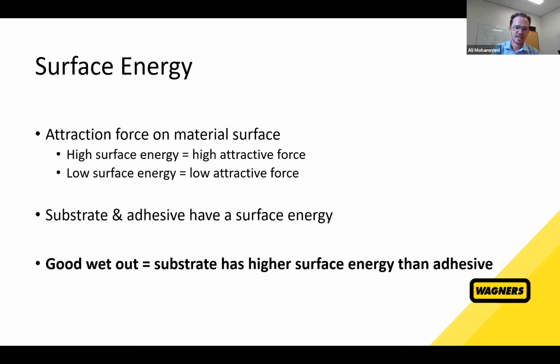And just to summarize, to get good wet out where you want the adhesive flowing across the surface well, you want a substrate with high surface energy. And ideally, it's a higher surface energy than the adhesive. High surface energy is a high attractive force. The adhesive is going to wet out the surface.